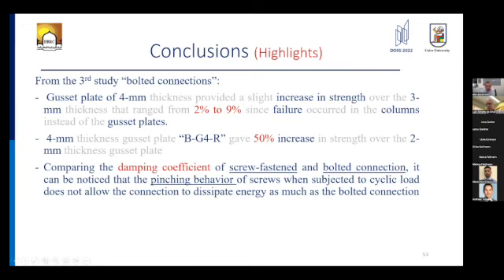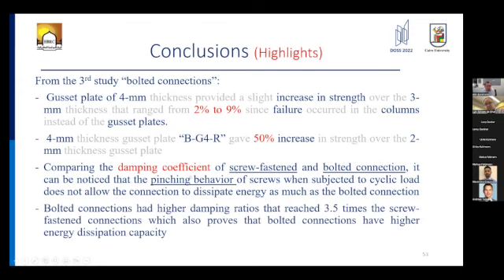A very important aspect I included in the study is the damping coefficient, which is another measure of the energy dissipation. You can see that the bolted connection can perform very well in dissipating energy compared, of course, to the self-drilling screws. This increase was 3.5 times.